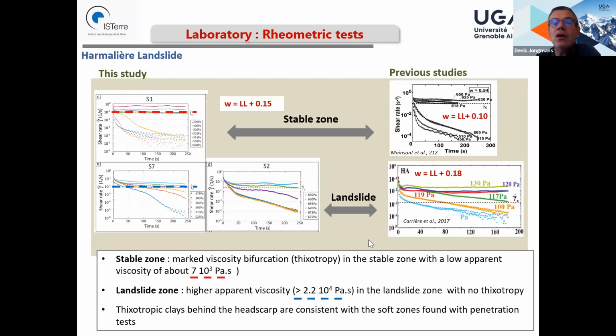And if we compare now with the previous study, so we found 2 previous studies made in the same area, in the stable zone and in the landslide, and you see that the authors found some similar results in terms of shape and in values. And so that gives us confidence in our results, which are the following: in the stable zone we have a marked viscosity bifurcation, meaning thixotropy of the clay in the stable zone.